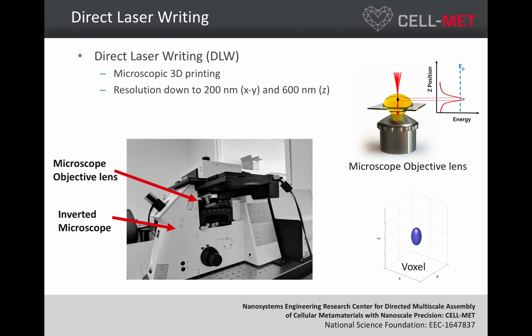So direct laser writing is related to stereolithography. It relies on focusing a laser beam into a light-sensitive material, and instead of everywhere that's exposed to the laser getting polymerized, you only have polymerization at the focal spot of the laser. So you're concentrating down all of this energy into a tiny focal spot, and this focal spot is known as a voxel. And so with this high concentration of energy, you're causing the liquid resist to solidify, to go through a chemical reaction. And when you have this happen, you can move it around using a mechanical stage, and you get really nice 3D printed structures.